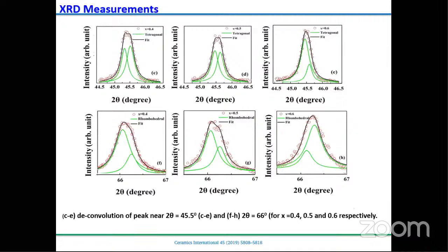Since there are two peaks at 45 degrees, and because this XRD is recorded at room temperature, we can say that these materials have the tetragonal phase. Similarly, if you expand at 65 or 66 degrees, here we can see two peaks. If there are no two peaks, then it is not rhombohedral. If two peaks are there, then we can say rhombohedral. So from this XRD, we have concluded that BCT and BZT, whatever material we have synthesized, consist of two phases, rhombohedral and tetragonal, at room temperature.